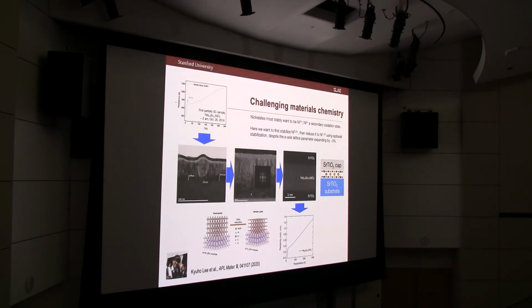And so we spent quite a bit of energy trying to grow and stabilize this interface phase. And kind of the final qualitative step or realization was that the substrate, in this case strontium titanate, which doesn't undergo this reduction chemistry, gives you a very nice proximity effect. It kind of templates over a few nanometers the orientation of this layered nickelate structure. So the final step for us was to think about making a heterostructure to cap this tri-layer with the same material such that we can orientationally stabilize this from both directions. And so what that allows us then is to get to single crystal thin films up to 10 to 15 nanometers.